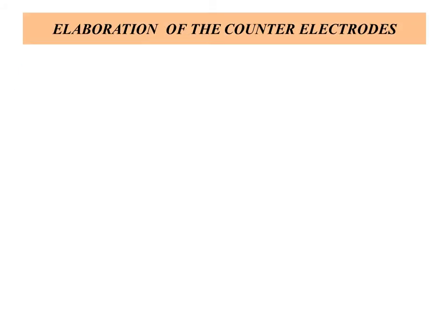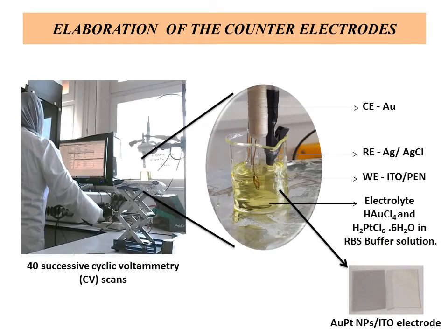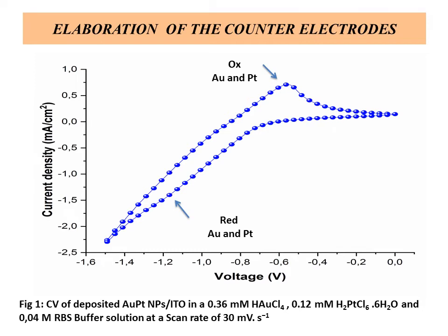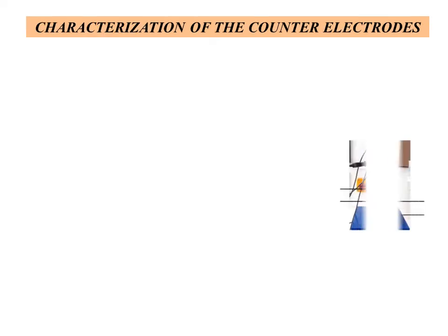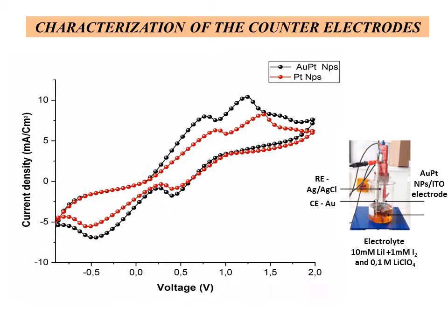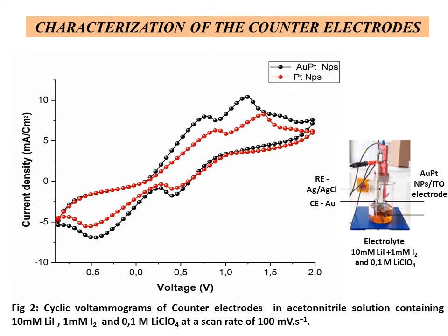To obtain flexible counter electrodes with excellent electrocatalytic performance, in this work we fabricated gold and platinum counter electrodes using an electrochemical method of 40 successive cyclic voltammetry scans. As shown in the cyclic voltammogram, the reduction peaks of gold and platinum appeared at about the same potential, at a scan rate of 30 mV per second. Cyclic voltammograms were obtained in this electrolyte using an electrochemical interface system at a scan rate of 100 mV per second. The electrochemical cells consist of the electrodeposited gold and platinum nanoparticle electrode as working electrode, gold as a counter electrode, and an AgCl as a reference electrode.